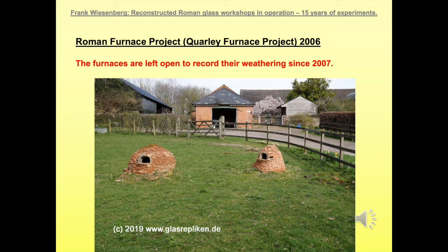Since 2007, the glass workshop at Quarley has been left open, exposed to the weather conditions as a sort of deterioration project. So the weathering of the glass furnaces is recorded regularly. As you can see, there is a lot of deterioration visible on the two big furnaces. And on the far right-hand corner, there are just the remains of the lehr, which was operated at a lower temperature. So this construction deteriorated much faster than the others, which were operated at higher temperatures, around 1000 degrees centigrade. This project delivers a lot of interesting data, which can be compared to the remains of Roman glass workshops from excavations.